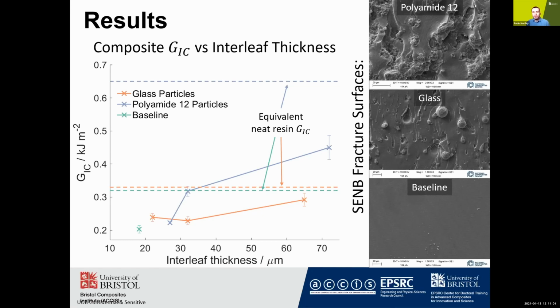Another takeaway is that particle material is crucial. These particles are not just acting as spacers to increase the thickness of the interleaf, and their properties are very important. And it would appear that beneficial properties would be a low yield stress and a high interfacial strength.